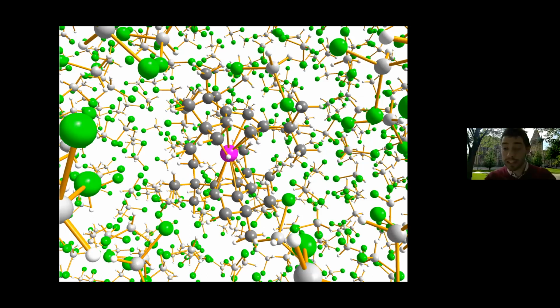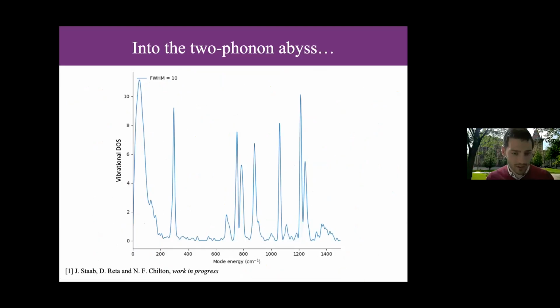So you can imagine that this really sucks as a computational chemist to try and optimize the geometry of this thing. And the meaning of that is also a bit questionable, but we can talk about that if you have questions. This is all preliminary, of course. We haven't actually finalized all of this, so this is just bleeding edge. But now this is the density of states we have for this sort of amorphous solution phase situation. And so instead of just having these discrete peaks, these big peaks correspond to the dichloromethane energy stretching, these little peaks are the single molecule magnet in the middle,